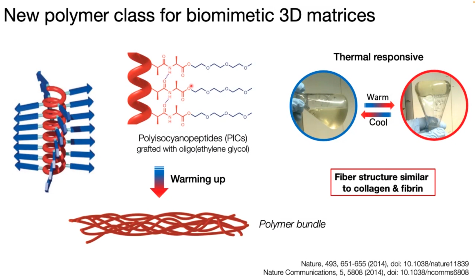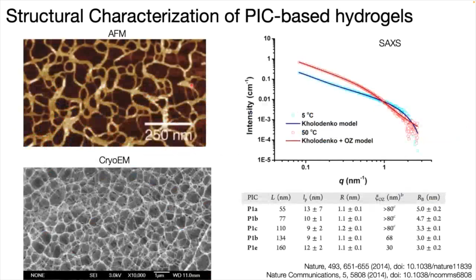But how does this fiber structure actually look? When we started working with this material, there were a few studies focused on trying to understand the structure of these PIC hydrogels. There was some work with AFM, and in that case, they just put a solution of the hydrogel on a mica surface, dry it, and then check what type of structure they have. So this is a completely dried sample. Then there is also cryo-EM, where again you have a fixed sample. Here you can really nicely see a porous structure. Here you have the scale bar. This is 1 micrometer, so they are very big pores.